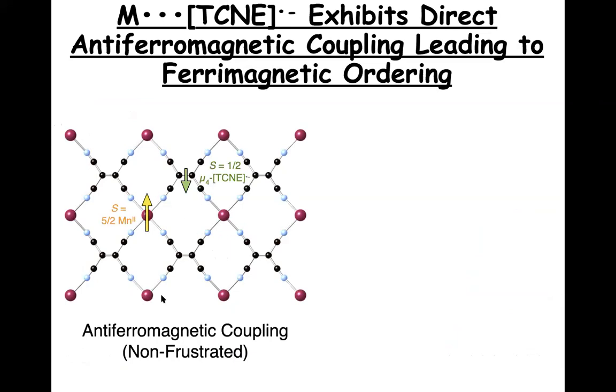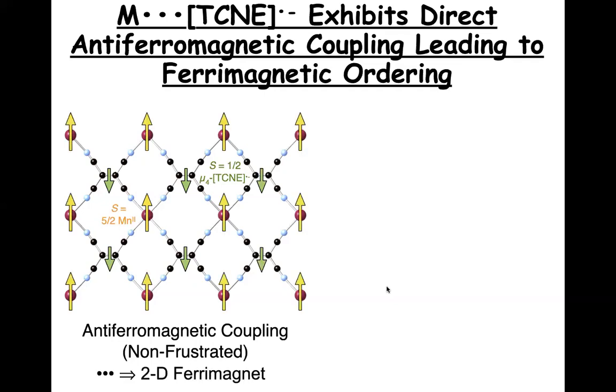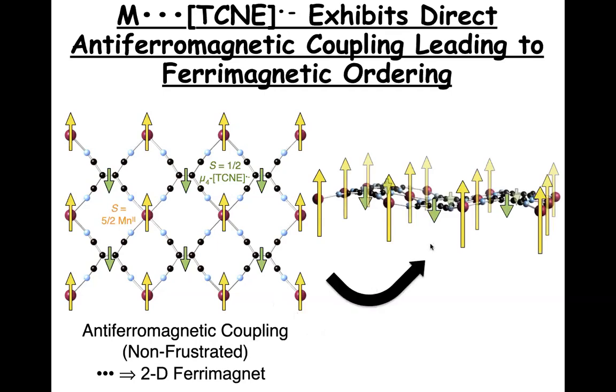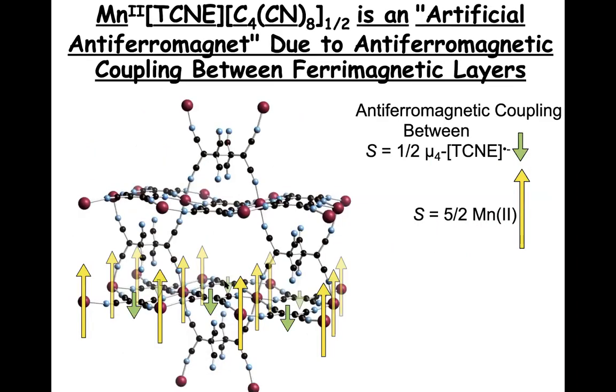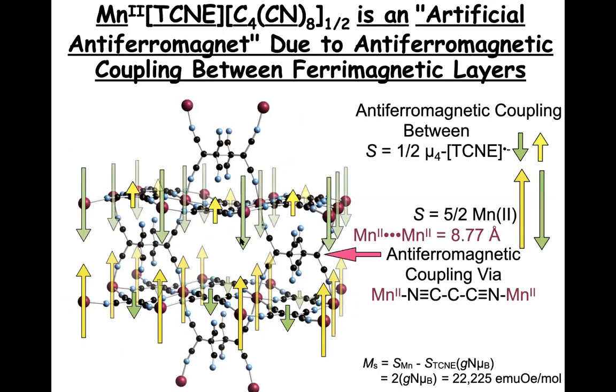But each manganese has 4 TCNEs around it. So all 4 spins on those 4 TCNEs couple antiferromagnetically. Each TCNE has 4 manganese around it, and each of those couple antiferromagnetically. So all the manganese spins are up, all the TCNE spins are down. Spin 5/2 antiferromagnetically couples with 1/2, leaves you with a planar 2-dimensional ferrimagnet, net 2 spins. So we're looking normal to the layer compound here, and now we're going to rotate it edgewise. So it looks like this. And now we're going to map that spin onto the structure, and you can see this ferrimagnetic layer over here, and it will antiferromagnetically couple to this next ferrimagnetic layer over here through this nitrogen, carbon, carbon, carbon, nitrogen linkage.